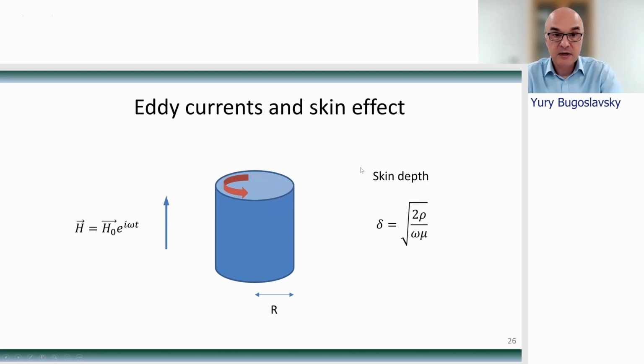I show you a conductor, for simplicity a cylinder, in an applied axial high-frequency magnetic field. And when we apply the field, it penetrates into the sample through the surface by inducing surface circular currents. The currents screen the field, and the characteristic penetration depth of the field is given by this formula for skin depth, which shows us that the penetration depth is proportional to the square root of resistivity and inversely proportional to the square root of frequency and magnetic permeability.